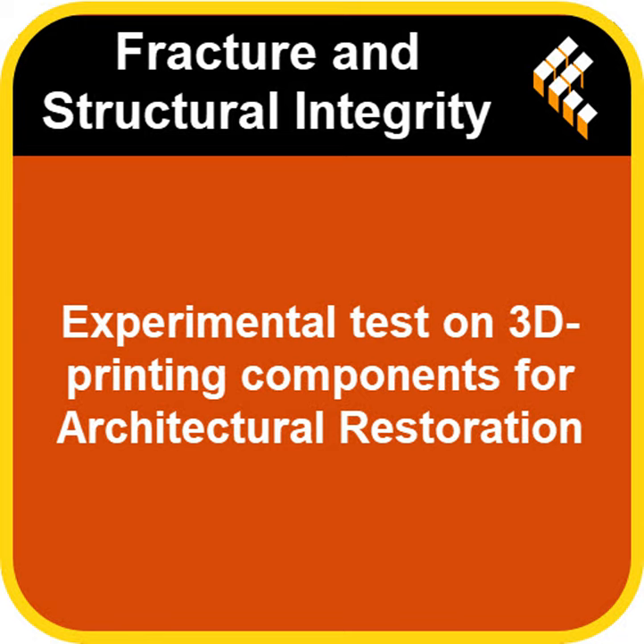Did that internal triangle angle matter in these tests? Interestingly, not really for the tension tests. Both the 60 and 72 degree designs behave very similarly. Stiffness was around 2.54 kilonewtons per millimeter. So it took about 2.5 kilonewtons of force to stretch it 1 millimeter.